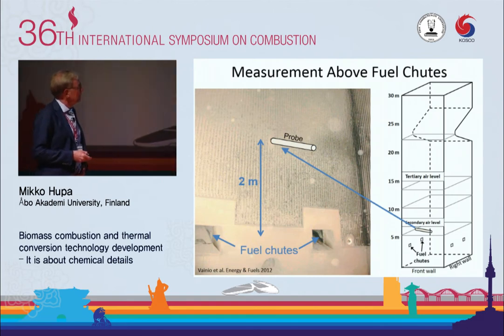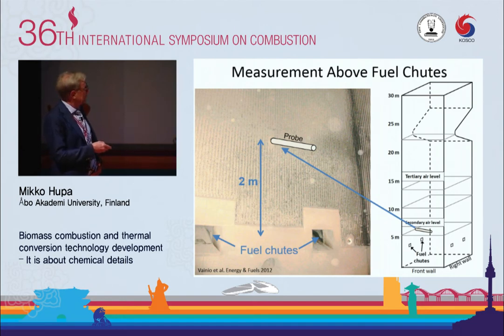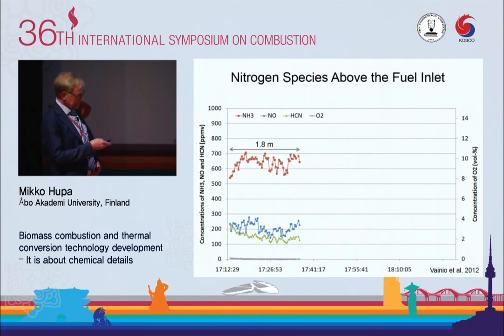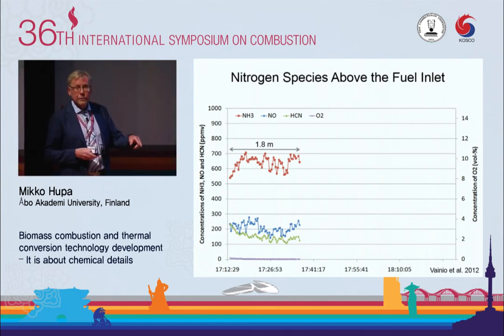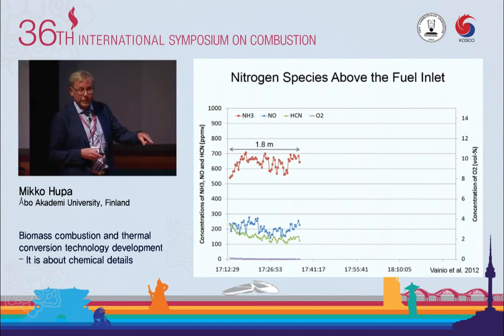Here you see an example where we located it inside such a huge furnace. Here are the fuel feeding chutes. The probe was 4 meters long, so we reached almost 2 meters into the furnace from different sides. And this kind of a signal we received. And you see that we could detect clearly ammonia. This is from that particular position in the lower furnace. So we found a lot of ammonia, and smaller amounts of NO and hydrogen cyanide.